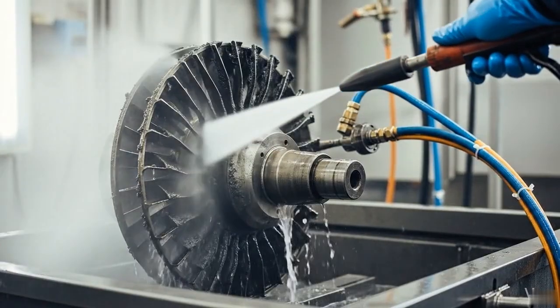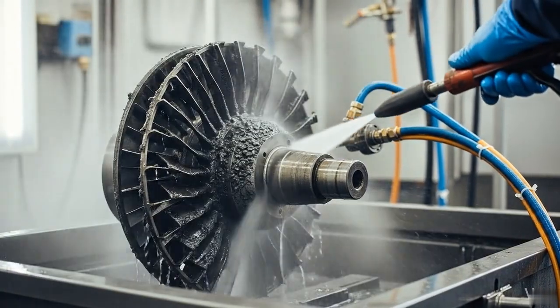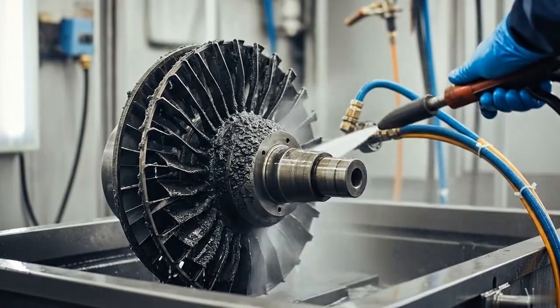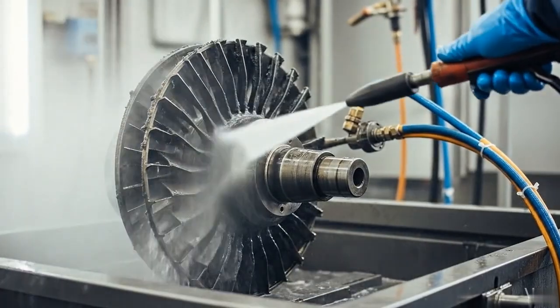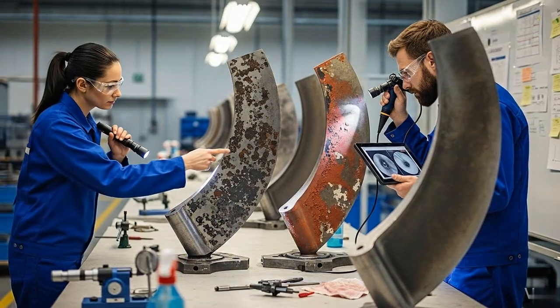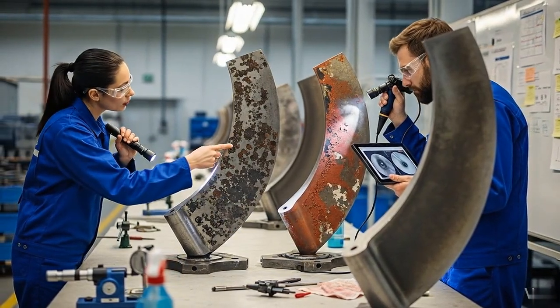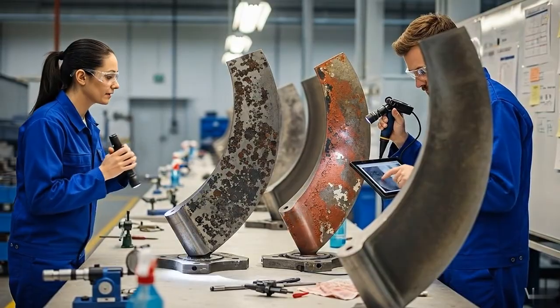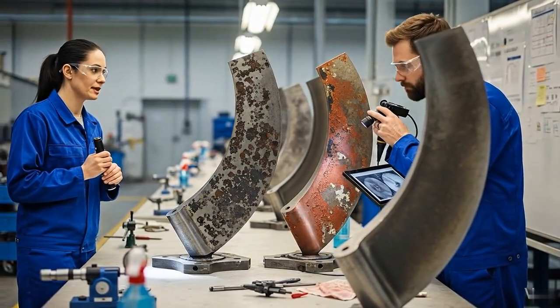Used blades undergo thorough cleaning to remove combustion deposits and contaminants, preparing them for detailed inspection and possible return to service. The oxidation depth here is significant. The coating degradation scan confirms it. This one is beyond refurbishment limits.